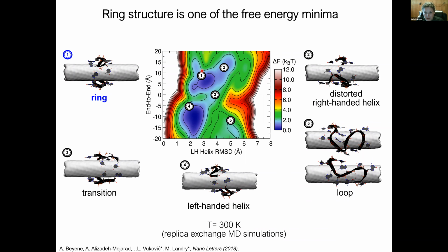We label them by conformations 1 and 4. So we can go back in our simulations and check what this basin of blue structure looks like. It turned out that this region labeled by 1 corresponds to the structures that do form ring conformations. And that is a free energy minimum structure. So this plot confirms ring structure is one of the free energy minima. The system also has another free energy minimum, which corresponded to the left-handed helix.